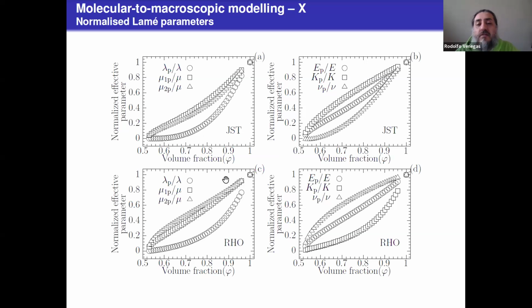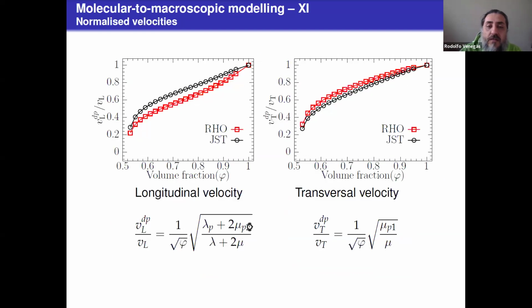There are interesting things happening in here where, for example, we have auxetic behavior for the substrate, but not for the double porosity material. So there is a critical volume fraction where this effect disappears. And it is slightly different in terms of Poisson ratio behavior. Then with this information, we can work out, let's say, normalized longitudinal velocity, normalized transverse velocity, and in that way, we can link the molecular scale with the velocities that we can measure at the macroscopic scale in a lab.